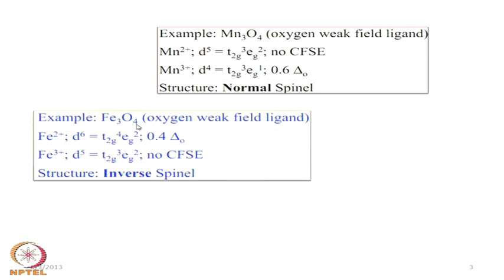Similarly, for Fe3O4, again with oxygen as a weak field ligand, Fe2+ gives stabilization due to the t2g4 eg2 arrangement. We have this d6 arrangement for Fe2+, so Fe2+ gives rise to a corresponding stabilization of 0.4 delta O, and for Fe3+ we have no CFSE, and this results basically in the inverse spinel structure.